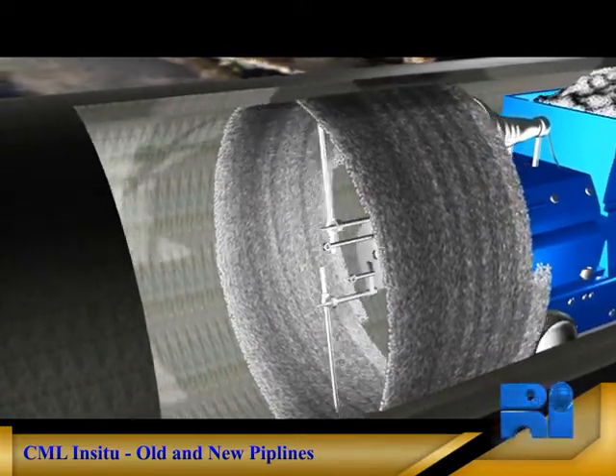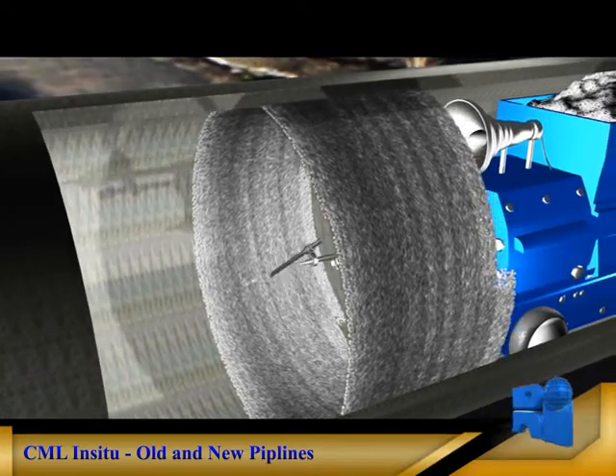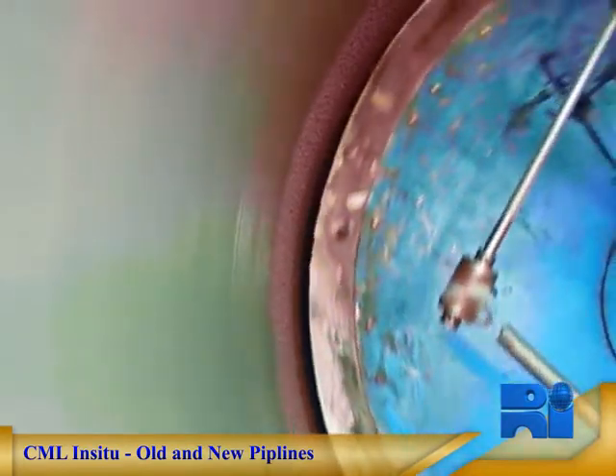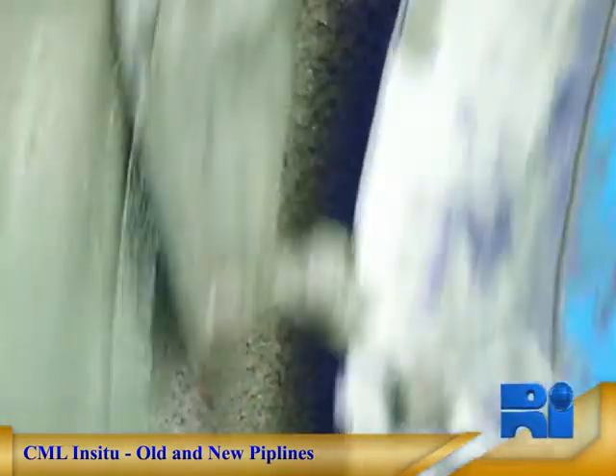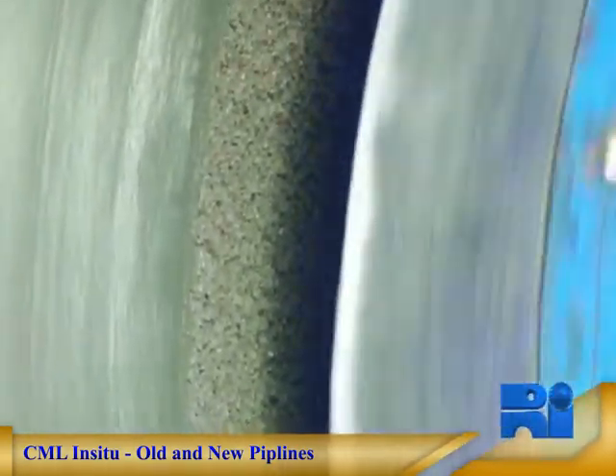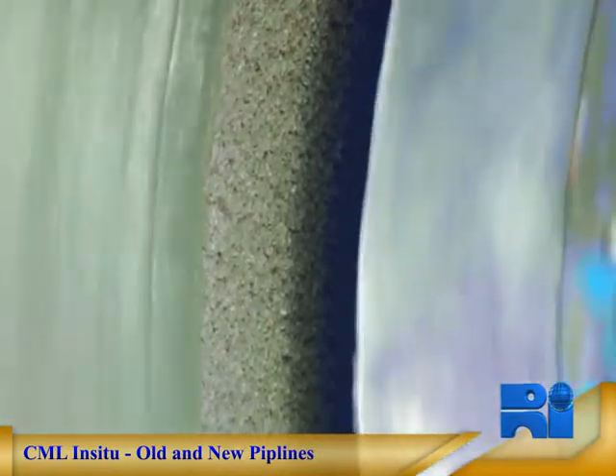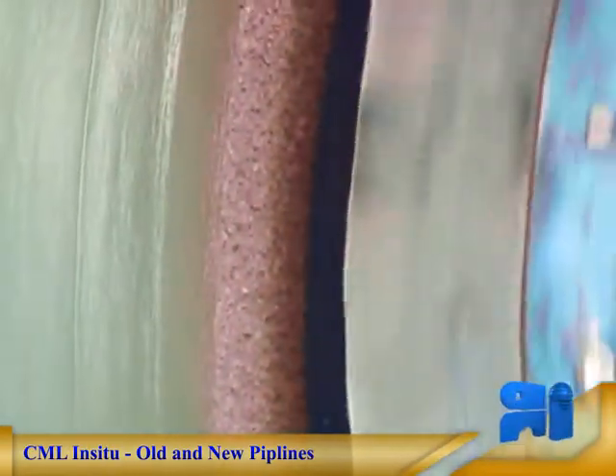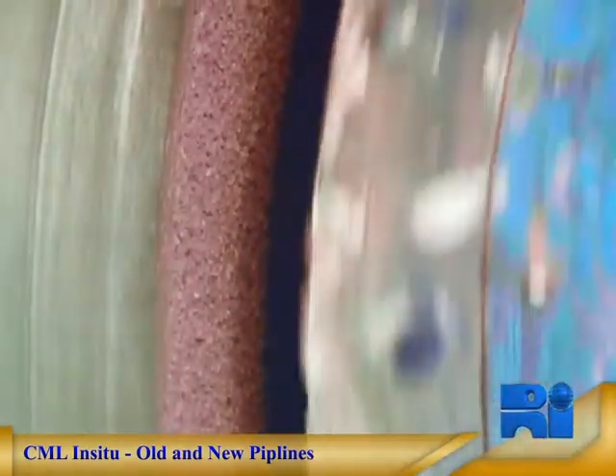Should any aggressive fluid seep through the lining of the pipe wall, it will have been rendered completely harmless from a corrosion point of view, owing to the free lime in the mortar, which converts the effluent into an alkaline solution. Inert, epoxy or urethane linings cannot offer chemical protection, and sooner or later the effluent will penetrate through pinholes, set up corroding zones at the pipe wall, and cause the lining to flake off.